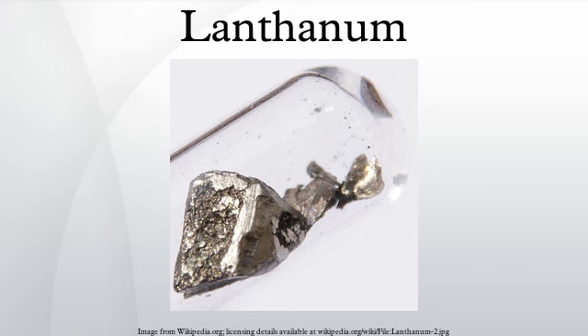Lanthanum oxide improves the alkali resistance of glass, and is used in making special optical glasses, such as infrared-absorbing glass, as well as camera and telescope lenses, because of the high refractive index and low dispersion of rare earth glasses. Lanthanum oxide is also used as a grain growth additive during the liquid phase sintering of silicon nitride and zirconium diboride.